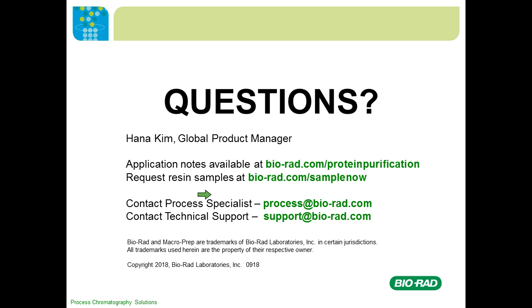And what buffers can be used for cleaning and sanitization? As you can see in my presentation, we used 0.5 molar sodium hydroxide for a 100 cycling study, and it had limited effect on the binding capacity. So we recommend 0.5 molar sodium hydroxide.